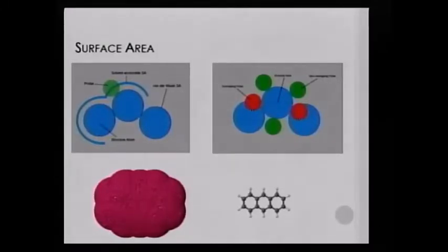So this is basically visualizations of what this surface area method does. And by doing so, we can estimate the surface area of the overall molecule, for example, which will be, of course, dependent on, for example, the radius of the probe you use. And this is interesting because this allows us to use different probe sizes to obtain different values of surface area. But you may ask, what is the true value? And the question is, there is none.